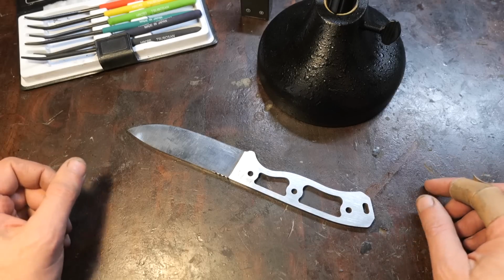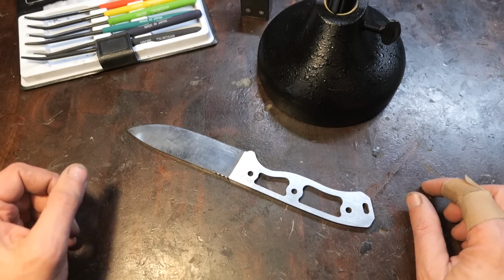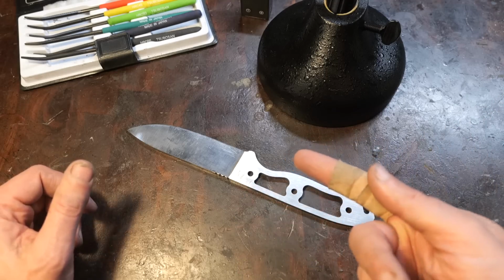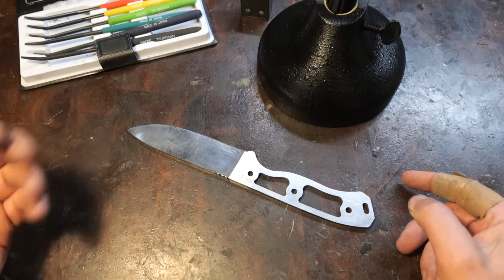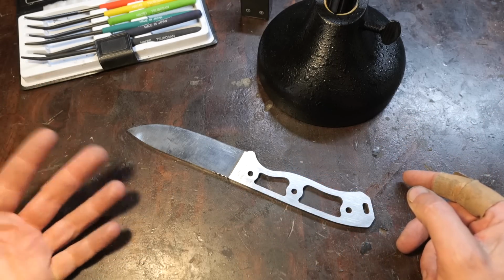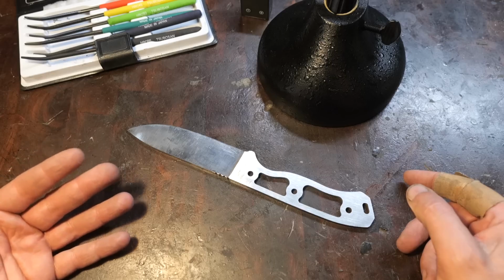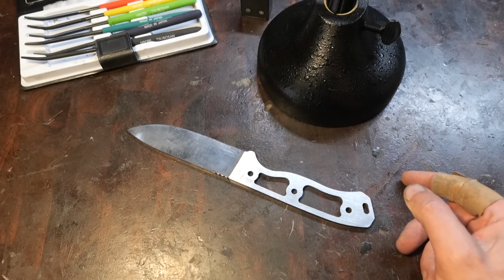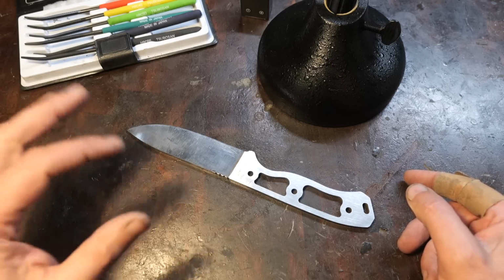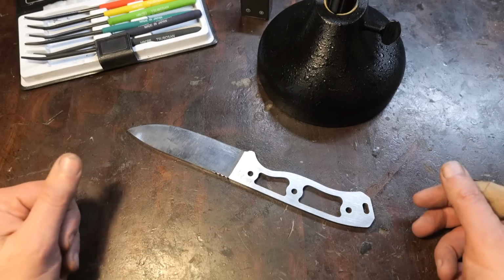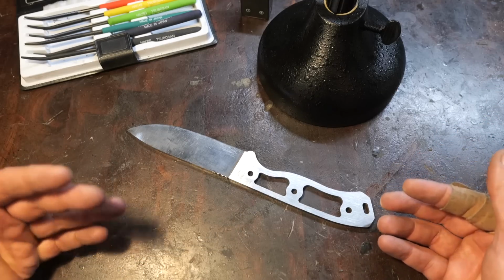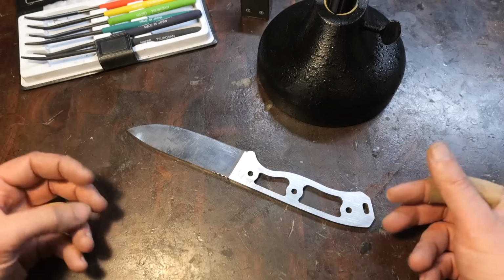All right, so if I had known the edge was going to last that long, I would have put the handles back on for that test because I tore up my finger pretty bad. We had 180, 190 cuts out of the box, and now we have over 500 cuts on sisal rope. How is that possible? Well, we've hardened the steel from 56, 57 range up to 60-ish, and we've reformed the edge to a geometry that is much more suited for slicing and cutting.